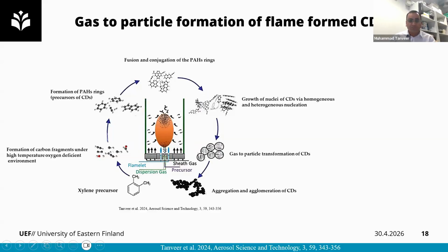Then these clusters start to undergo homogeneous and heterogeneous nucleation, because at this stage the supersaturation condition is achieved and particles start to grow. Following this stage, particle evolution starts, and we can get nanometer-size particles. Then when these carbon nanostructures are exposed to a low temperature region or room temperature, they start to aggregate and agglomerate. So this is the whole mechanism of how particles grow inside this closed flame process.